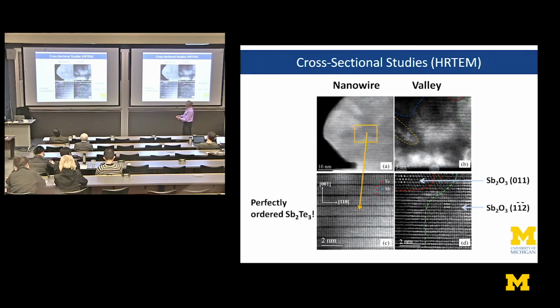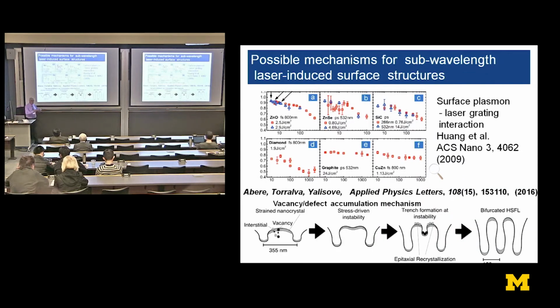This has got 011 orientation. This is 1 bar, 2 bar. And not only that, it's not antimony telluride anymore, it's antimony oxide. And that means that all the tellurium that was in these valley regions was exchanged for oxygen from the atmosphere in which we did the laser illumination. So instead of antimony telluride, we now have antimony oxide. Antimony oxide happens to be an insulator, and that means that since the nanowire, being a very narrow bandgap material, is highly conducting at room temperature, almost like a metal, we have actual wires separated by insulating regions all the way down to the substrate.